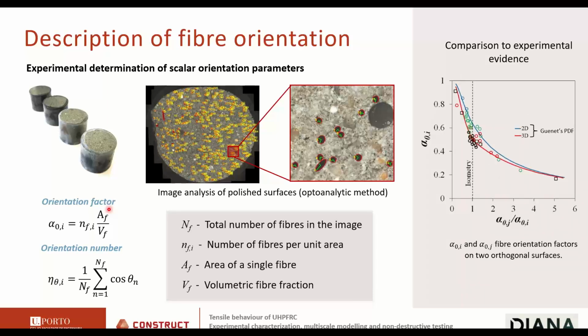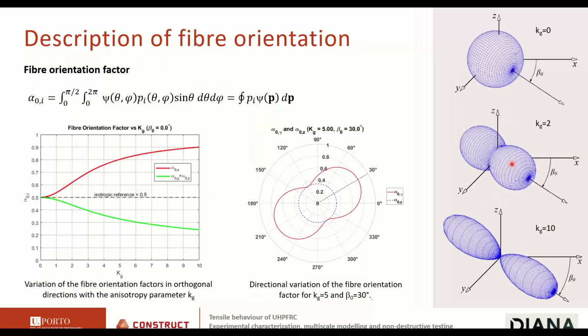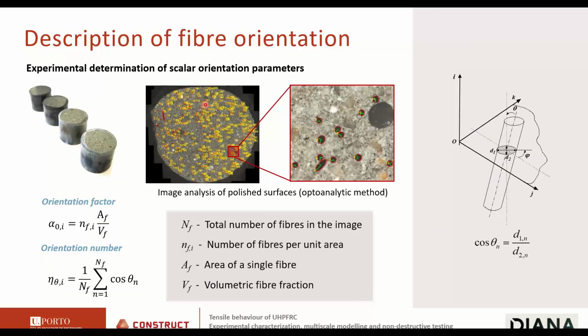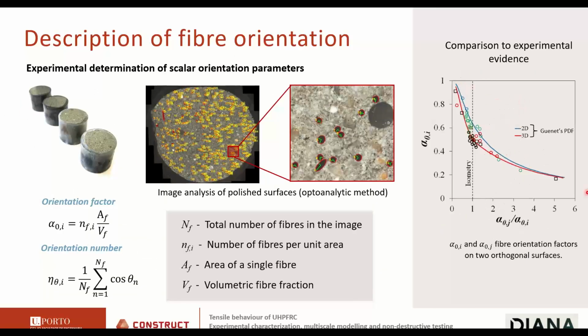And then we can compare what we measure in our specimen. So we did a lot of work orienting the fibers, and so we have a lot of data. And you see here the dots are the experimental data points, okay? And the lines are the predictions obtained using this equation. We see that, okay, it's not too bad. So the equation fits well what we observe.